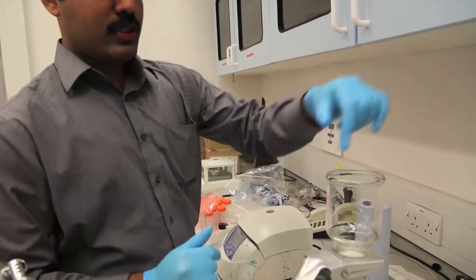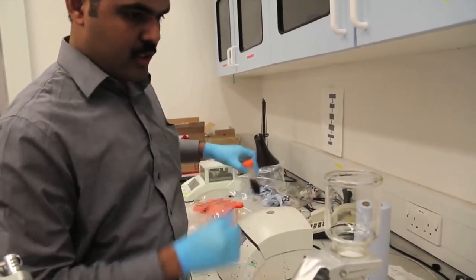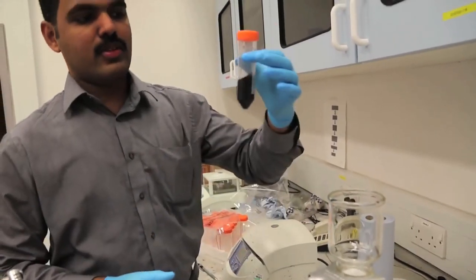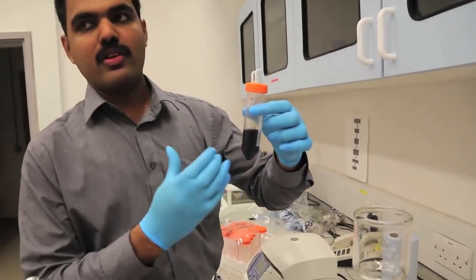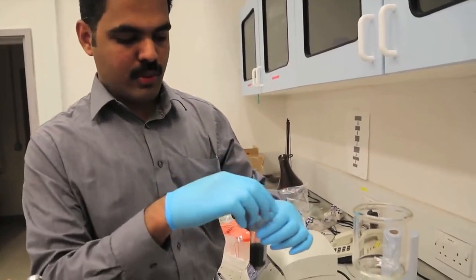So you use porous support there, then you pour graphene oxide solution over here. So this is a graphene oxide solution in water. It has single layer graphene oxide dispersed in pure water.